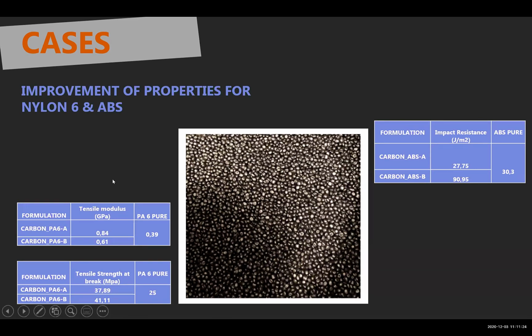In the meantime, when we are talking about nylon 6 polyamides, we have this difference too. There are two ways that we are looking at to develop this masterbatch. If you compare A and B, you can see a difference, but you can see that we can increase even the tensile modulus and tensile strength. So this is a good result. And we keep going with this development, because we strongly believe that for engineering polymers, it's a good market to develop graphene and graphene oxide.